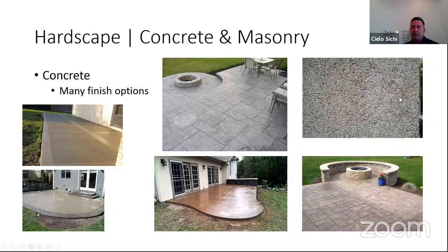There's a lot of ways to achieve this. The newest, latest, greatest way is a product called Top Cast. It's essentially a surface retardant where after the concrete is laid and finished, a chemical gets painted onto it, and it retards the curing, or prevents the curing, at the very top portion of the concrete. So the cement doesn't cure there. And the next day you power wash it off, and you wash off that chemical as well as what's called the cream portion of the cement. You end up with this sand finish. This is a very heavy sand finish.